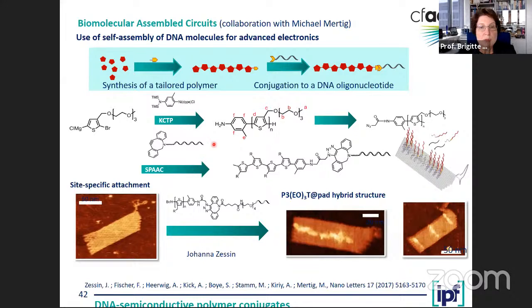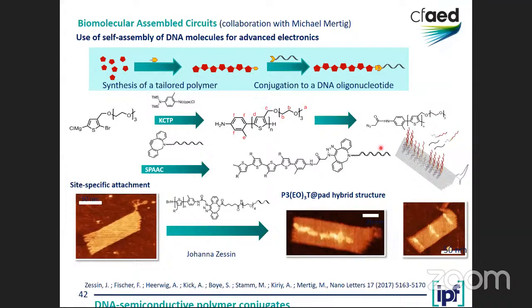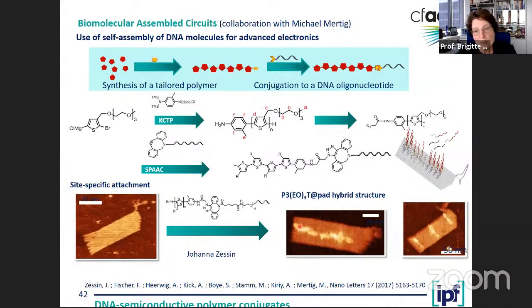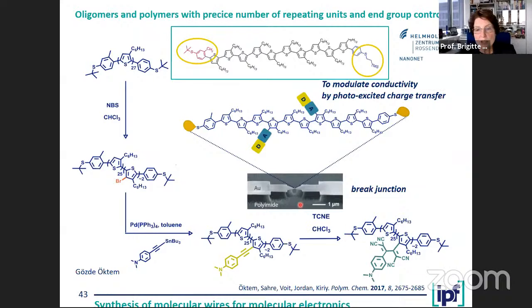For example, we made polythiophene, which we conjugated to DNA. And then you have, again, a hybrid material. And this hybrid material was used to decorate DNA origami with such conducting layers and stripes. So that is actually a DNA origami. You might know that you can assemble specific DNA strands into defined structures by designing the DNA. And when you have a DNA strand which is complementary to some of those DNA strands here, you get site-specific attachment of the hybrids we used here. And you can make oligomers, which are interesting for nanoelectronics. So you can make attachment points on such a molecule, which even can have additional donor acceptor moieties, and put them as single nano macromolecules here for making devices on a nanometer scale.